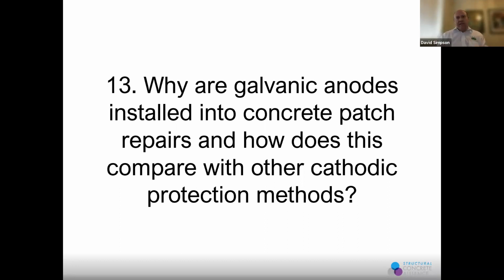and put back a nice, fresh repair material to 1504, with high alkalinity. The steel in that patch is now only going to be passive. But what we've left behind, and this is typically the case when we look at chloride more than anything, is parent concrete that still has corrosion or chloride in it. Therefore, you're setting up a potential difference, a drive voltage, between the old and the new. With time, you tend to find that the outside corrodes and protects the patch. That's what we call the incipient anode formation.